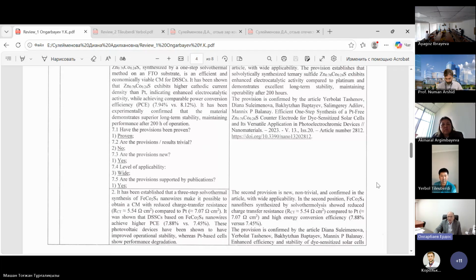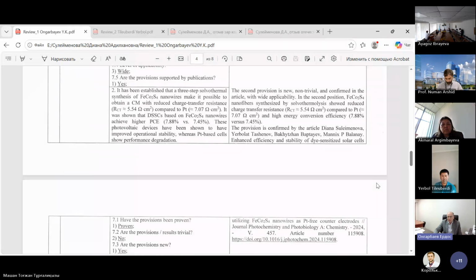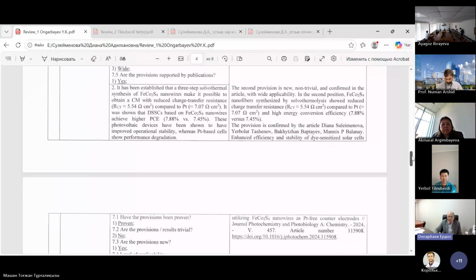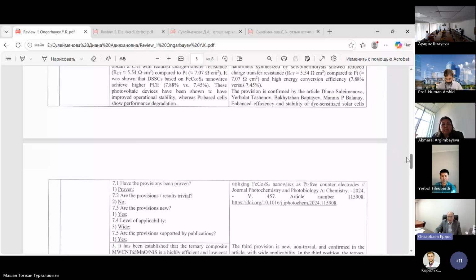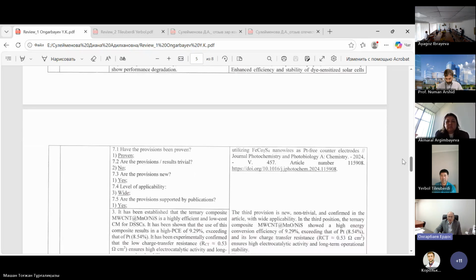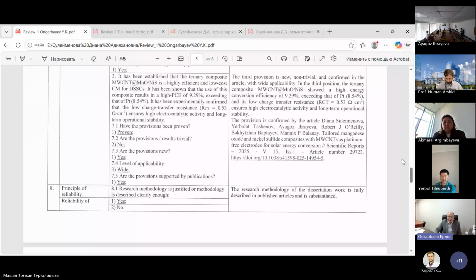The second provision is new, non-trivial, and confirmed in the article with wide applicability. In the second provision, iron cobalt sulfide nanowires synthesized by solvothermolysis showed reduced charge transfer resistance compared to platinum and a high energy conversion efficiency. This provision is confirmed by the article published in the journal Photochemistry and Photobiology A: Chemistry 2024. The third provision is new, non-trivial, and confirmed in the article with wide applicability. In the third provision, the ternary composite showed a high energy conversion efficiency of 9.29%, exceeding that of platinum, and its low charge transfer resistance ensures high electrocatalytic activity and long-term operational stability. The provision is confirmed by the article published in Scientific Reports 2025.